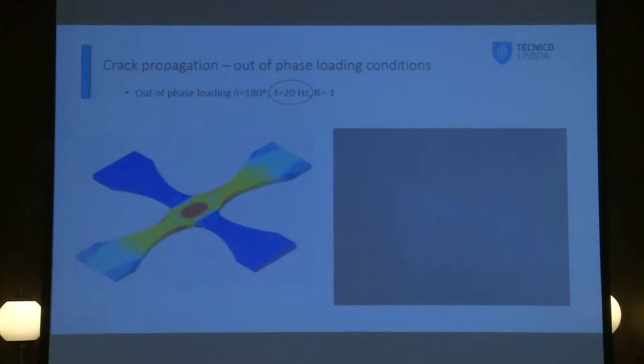Here, another kind of test that we have is the biaxial fatigue with in-plane specimen. As you can see here, we have four independent engines. And here, the microscope that allows us to monitor the crack initiation and the crack growth. As you can see here, maybe you can notice it here and here. This is just an example to see. This is an out of phase, 180 degrees, because the engines are independent.